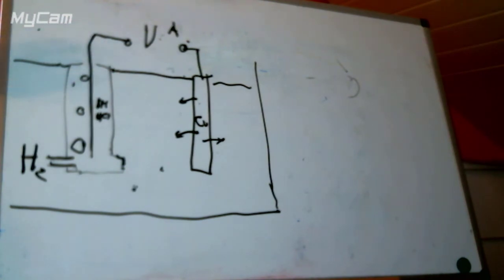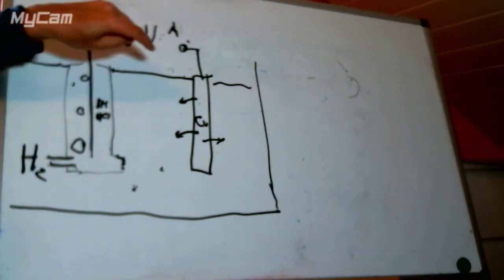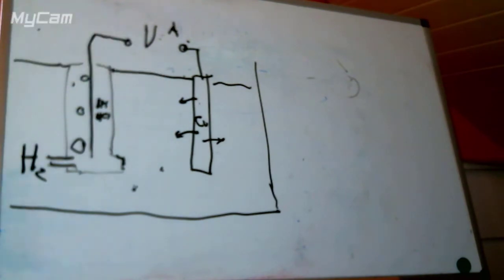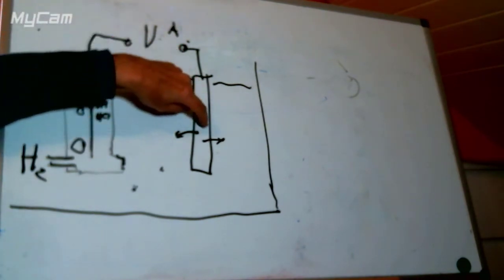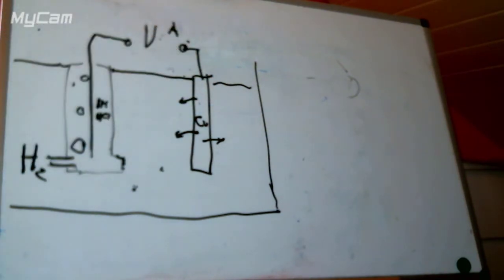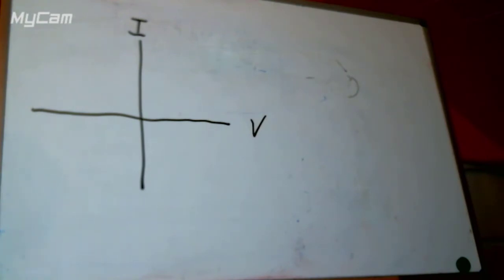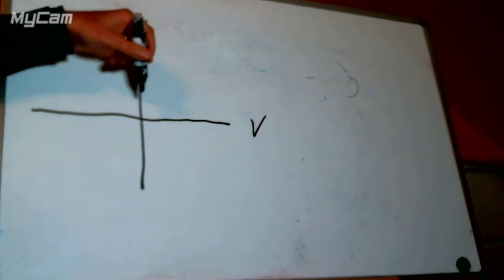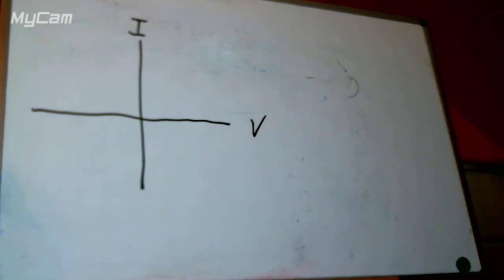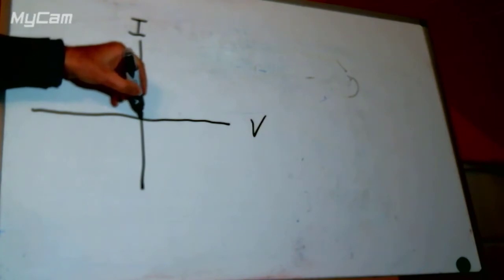Let us look at it a little bit further. The good thing about copper is it doesn't have a copper oxide layer if we control the solution properly, which is why I haven't defined it very well deliberately, so that we can imagine this copper to be bare metal. In most cases, it's not bare metal, it's got something on it. So if we do a simple experiment and we take some copper, we put it into copper sulfate solution, so that we've got plenty of copper ions in solution and we've got plenty of copper that can dissolve, and we just think about the one electrode, so we have to use a reference electrode for this.